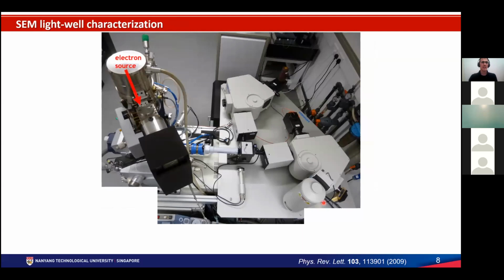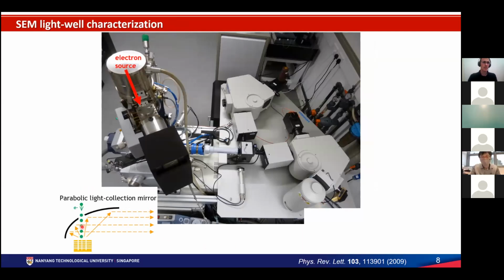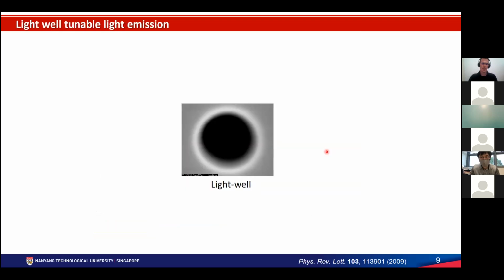We shine the electron beam, and it goes through the hole in a parabolic mirror, goes through the well and generates light, which is collected by the parabolic mirror and sent to a spectrometer, and finally the spectrum is detected by a CCD array. The technique is called cathodoluminescence spectroscopy. What we did was raster scan the electron beam across the light well so that we could see the emission regime depending on where you are illuminating the well.